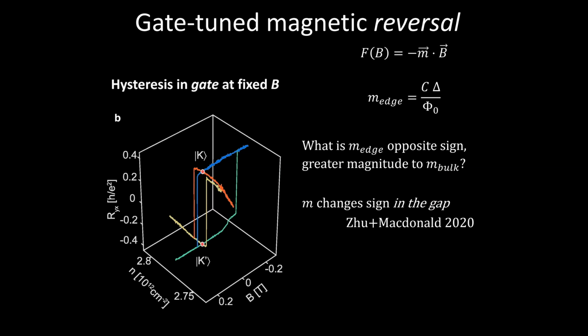But in these systems, this magnetization actually has contributions from the bulk, and it also has contributions from the edge. And it so happens that the bulk contributions in this system have one sign, and the contribution from the edge, which is proportional to the Chern number and the size of that energy gap, has the opposite sign, which means that just by populating an edge state, you can go from having a positive magnetization in one valley to having a negative magnetization in that valley. So if you're at some field, you were in the ground state, and now all you did was populate a little bit of edge magnetic moment, and now you're no longer in the ground state. You're now in this disfavored state, and you'll get relaxation.